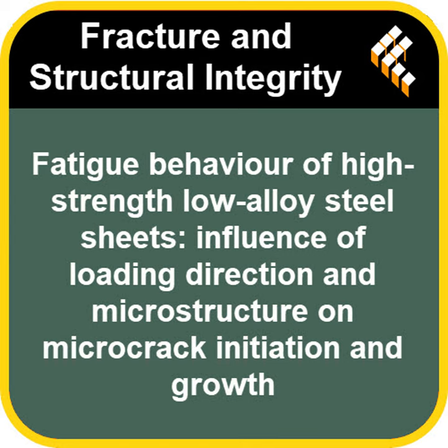The transverse direction, TD, specimens consistently across all the strain levels they tested had the shortest fatigue life. How much shorter? Significantly. At low plastic strain, the RD samples lasted almost twice as long as TD. Even at the high strain level, RD still had about a 25% longer life than TD. Wow. And DD, the diagonal.